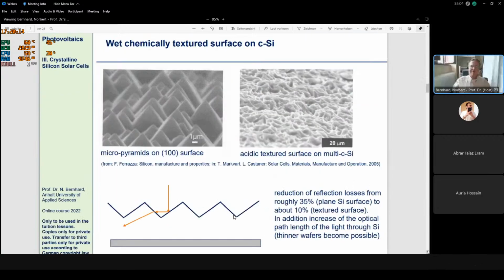Okay, I promise to explain why we need this wet chemical texturing of the silicon surface. First, I want to show you two SEM pictures, scanning electron microscopy pictures. You see, that would be the alkaline etch. If you use an alkaline etchant, we get these micropyramids on a 100 surface. But here I should mention for photovoltaics, if one has monocrystalline silicon, it's always a 100 surface, and this surface is also by far the most widely used in microelectronics. That means this is basically the standard surface which is used for device manufacturing in both photovoltaics and microelectronics.